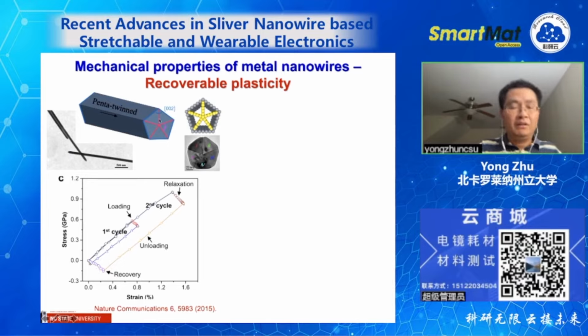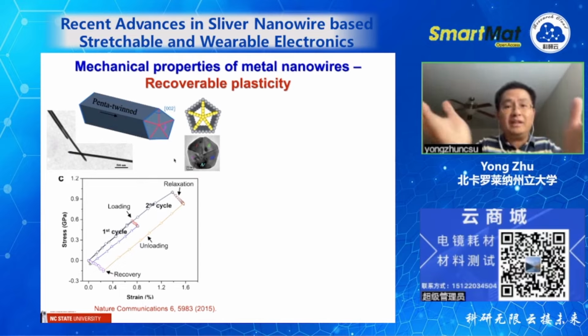The reason is that for all these nanostructures, almost always the dislocation is nucleated from the surface. But in this case, you have twin boundaries. They will block the dislocations, and when you unload, the dislocation will go back. That's good, right? That's an advantage for stretchable electronics. When we stretch them, they will deform, but when we release, they can come back.